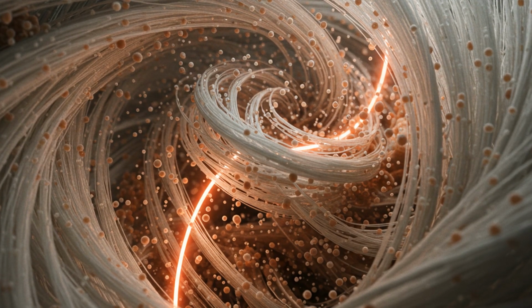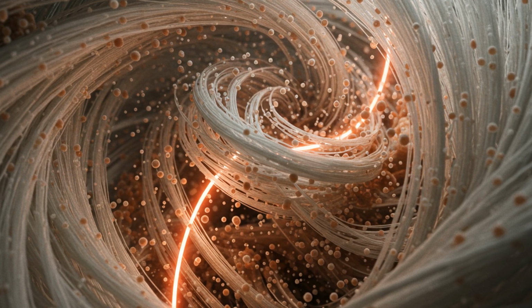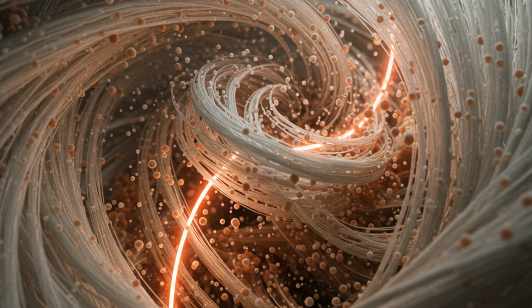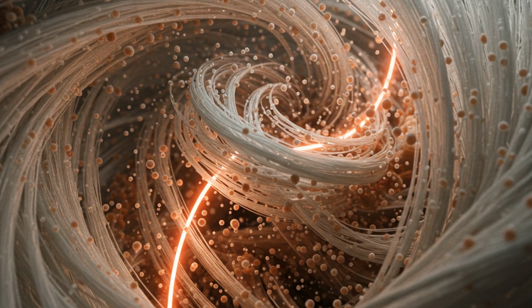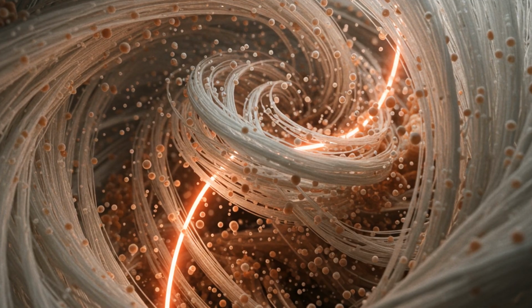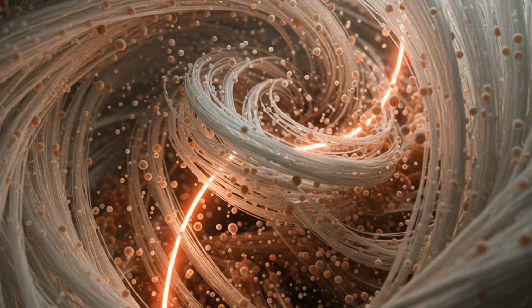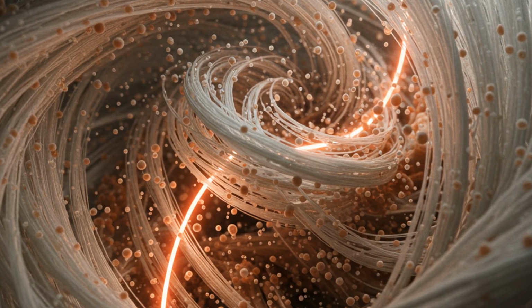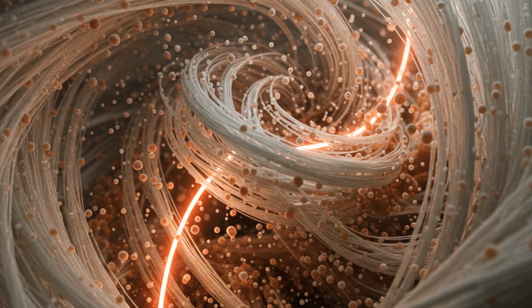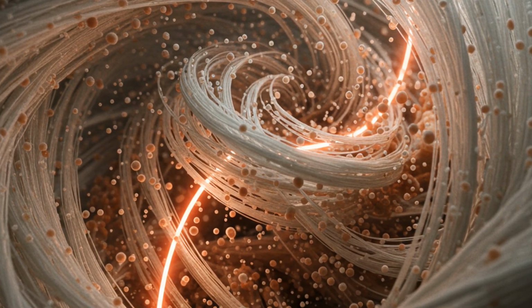But the real magic happens with the smallest particles, those below 0.1 microns. These aren't just blown by the wind, they are bombarded by air molecules, causing them to move in a zigzag pattern called Brownian motion. This chaotic movement, diffusion, virtually guarantees that the smallest particles will eventually strike a fiber. This is why HEPA filters are paradoxically more efficient at the smallest scales. The most difficult particles to catch are actually the middle-sized ones, around 0.3 microns, which is why that specific size is used to rate a filter's efficiency.